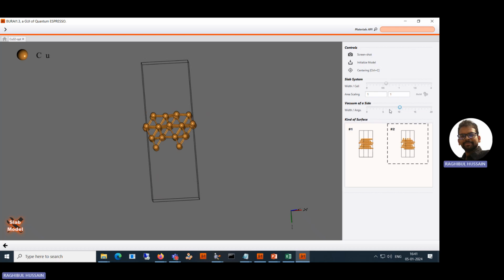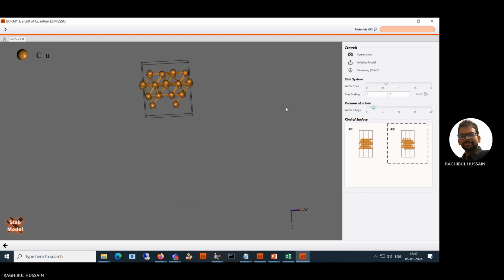And also, since it is a periodic system, whatever box size you see, you can assume a similar box nearby, similar boxes up and above in all directions. That is why, if you are doing the surface reaction over that top surface and you are reducing this box size, and you are placing a molecule here, suppose this direction is 0.5 angstrom, here also 0.5 angstrom. So between the same molecule, you will find a 1 angstrom distance. So it will create an interaction between the same image.